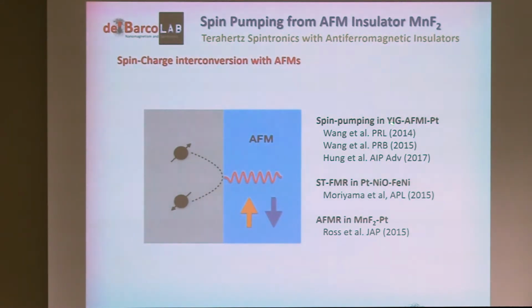YIG, yttrium iron garnet, with the antiferromagnet sandwiched in between the ferromagnet and the heavy metal, and spin dynamics generated in the ferromagnet, transported through the antiferromagnet into the platinum and then interconverted into charge. The other thing that has been done is spin transfer FMR in this heterostructure. It is related, but it's not directly spin pumping.